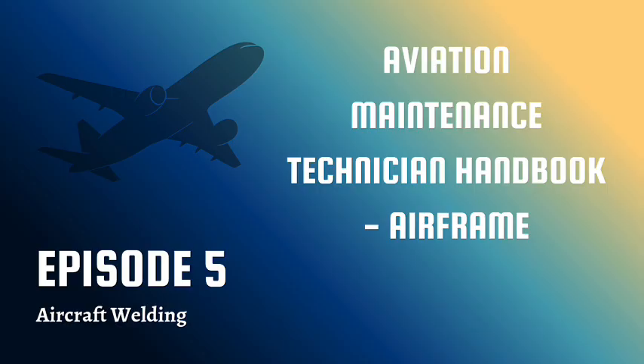Historically, SMAW was used effectively in aircraft manufacturing. The example often cited is Stinson, who used stick welding for their 4130 steel fuselage structures back in the day. However, and this is important, those welded structures absolutely required careful, mandatory heat treatment processes after welding to relieve stresses and refine the grain structure affected by the high heat input.